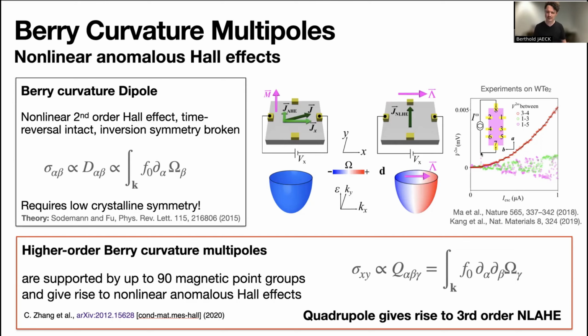And in the meanwhile, our understanding of these multipole effects has been growing. It turns out that while this specific dipole needs a very low crystalline symmetry, I believe here in tungsten telluride just one mirror plane, antiferromagnets can host a larger variety of multipole effects. In fact, it was predicted by my dear colleague Yang Gao here at HKUST that up to 90 magnetic point groups in antiferromagnets can give rise to various types of nonlinear anomalous Hall effects. In other words, 90 magnetic point groups support different types of Berry curvature multipoles. Today, I will talk about the Berry curvature quadrupole, which is predicted to induce a third-order nonlinear anomalous Hall effect.